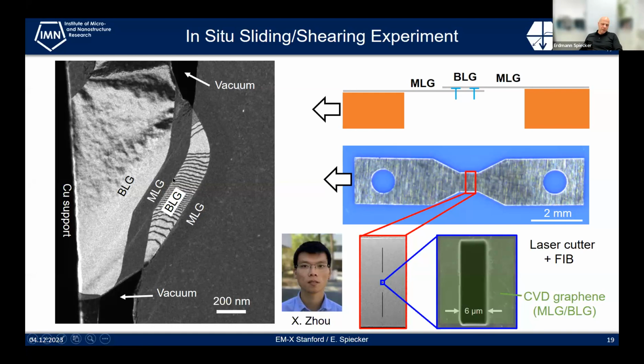So you see here a bilayer graphene stripe, and on the left and on the right you see monolayer graphene, and obviously the bilayer graphene has been disconnected from the monolayer graphene on the left side and slid already a little bit to the right. So we have exactly the situation that is shown on the top right, that one monolayer graphene, let's say the top monolayer graphene is on the right, and on the left it's the bottom monolayer graphene, and in between we have the overlapping graphene layers, which make the bilayer graphene region.